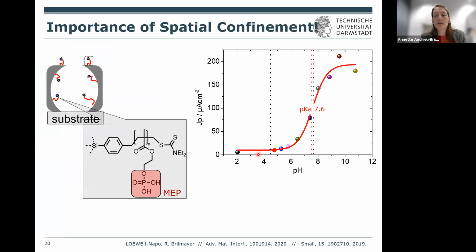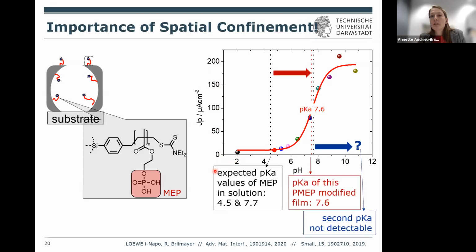And this is again an interesting topic in the nanopore community in terms of theoretical work, and there are very few examples of experimental work. We investigated this on the phosphate containing polymer by doing titration curves using cyclic voltammetry. So basically the same transport data that you saw before, plotting the maximum of that curve against the pH value that you can adjust in the solution in the pore, to get information on what happens inside the pore. What you would expect is a pKa value for MEP at 4.5 and 7.7. What we observe is the first pKa value at 7.6, so strongly shifted. And the second pKa value for this system we could not detect anymore because at some point we have stability problems.